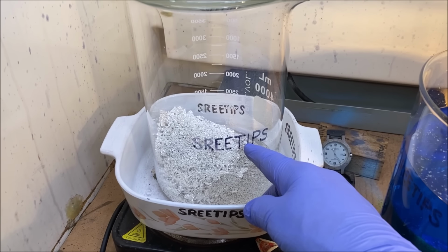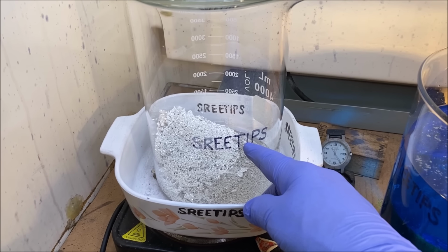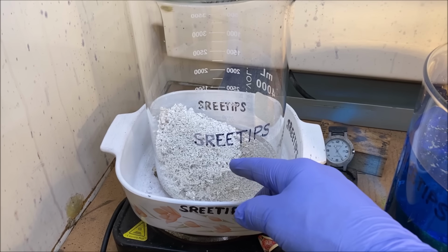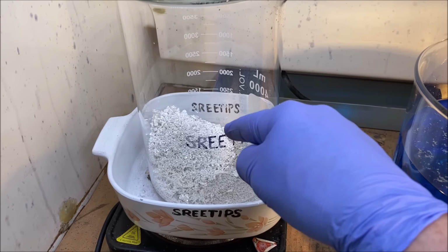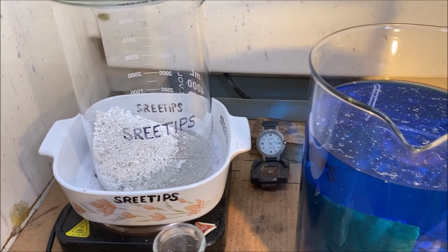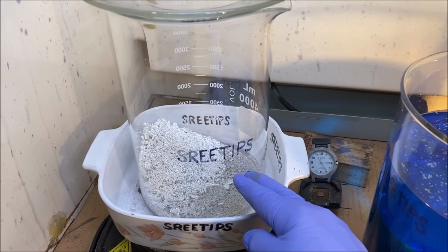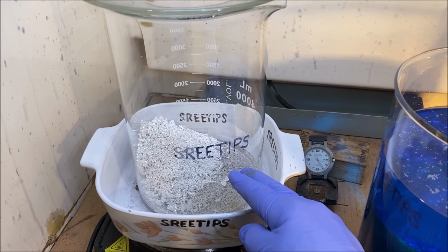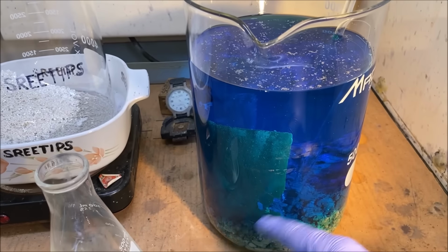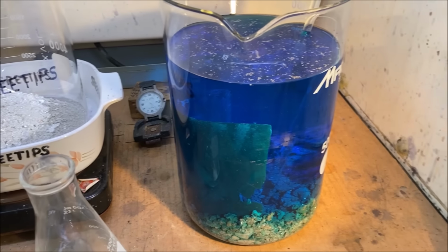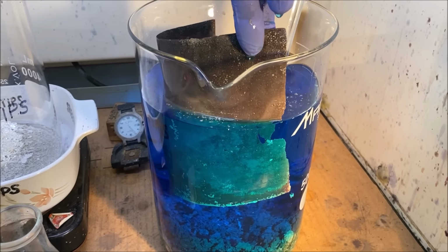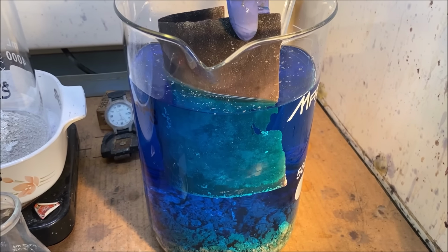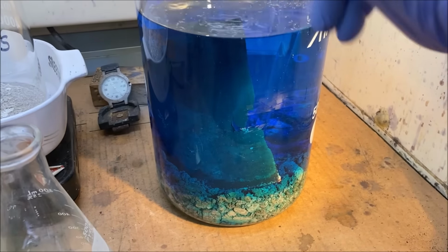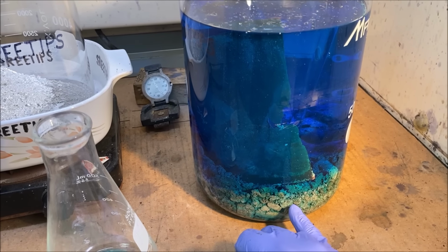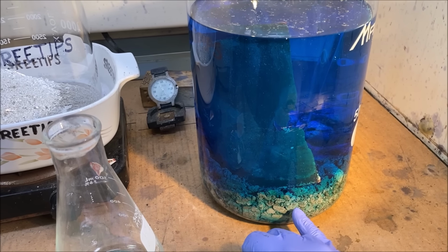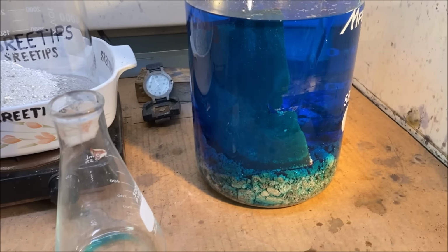It will tend to deposit on the cathode as the silver cell runs, and will turn right back into pure silver crystal. But I need this to form the electrolyte to allow the silver cell to run. Any of the silver in here that doesn't get deposited on the cathode will end up as spent electrolyte like this. I just add this little piece of copper in here and cement the silver out of the solution. Then I'll use the cemented silver down here, take it out, rinse all the blue liquid off of it, melt it in the shot, and then run it through the electrolytic silver cell.